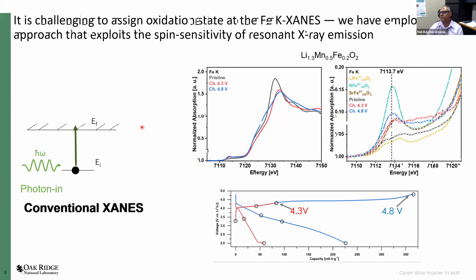So understanding oxidation state based purely on X-ray absorption is a little bit challenging. However, we also know that particularly in the case of iron, the X-ray emission is quite sensitive to the spin state of the ion. And one might be able to link the spin state with the oxidation state. And so we have tried to integrate X-ray absorption spectroscopy and X-ray emission spectroscopy to understand charge balance phenomena in this material.